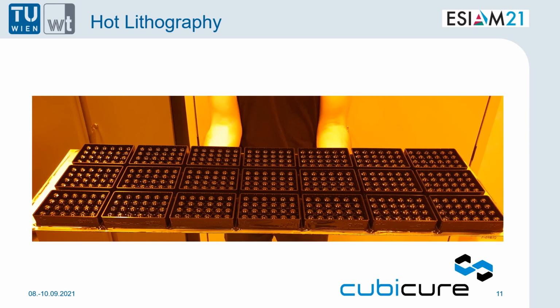This revolutionary printing system transmits minimum peeling force to the printed parts and therefore allows the printing of most delicate structures up to large volume parts over a length of 1 meter. But further, because of the easy access to the whole printing area during printing, this technology can easily be used as a base for a combined printing system.